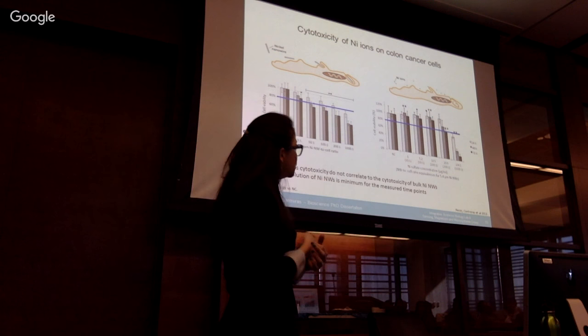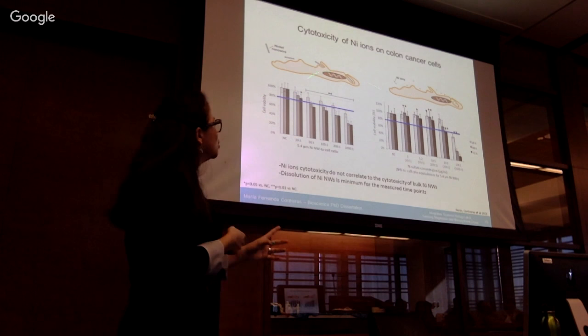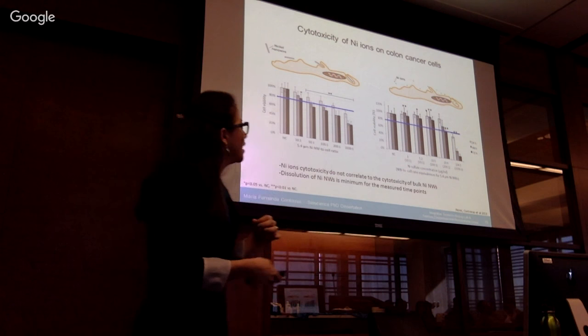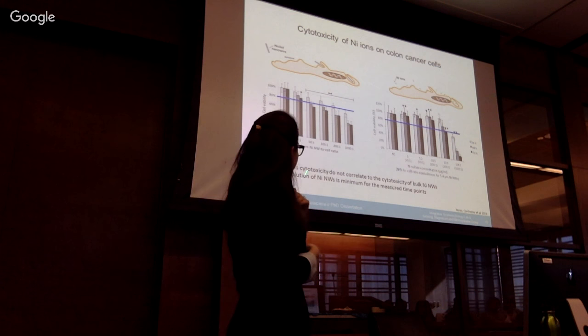So the toxicity is more attributed to, let's say, the shape and the bulk form, the solid form of the nickel, rather than to its ionic form. So yeah, the dissolution here is very minimal for the measured times of our experiment.